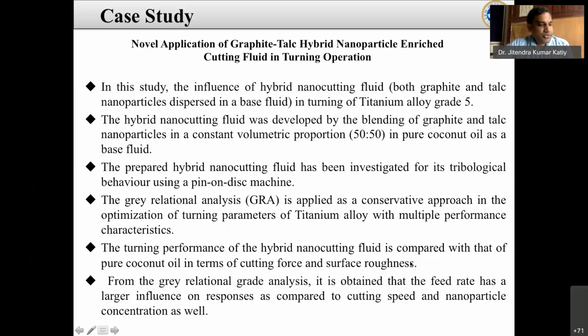After that, I performed the GRA analysis because in titanium alloys, from the GRA, grey relational analysis, we can get the optimum output parameters. The main optimum output parameters are surface roughness and material removal rate. Those are the two output parameters which I consider in this study.